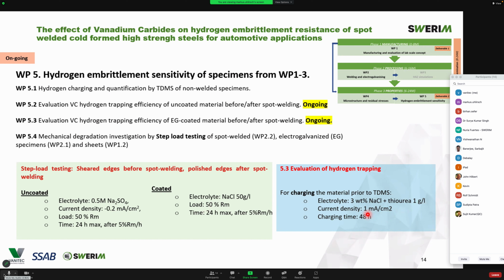First of all, we have not used any recombination poison for the mechanical degradation test. As you can see in the green box, it's solely electrolyte, which is probably not so corrosive. Of course it's corrosive, but for the coated sample it's simply sodium chloride, and the reaction we expect there that produces hydrogen is basically the galvanic effect between the zinc and the sheared edges of the metal. On the uncoated sample, we used sodium sulfate without any recombination poison and very mild current densities that, from our experience, we know would charge hydrogen slowly, so no strong effect will be there.